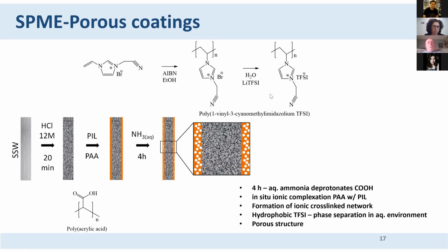So we made, first we etched the wire. We etched the wire, then we dipped it in the solution. So it was a 1-to-1 in weight solution. And then we put this inside of an aqueous solution of ammonia. And what happened was that in situ complexation of the polyacrylic acid occurred since it deprotonates. And so it binds to the PIL and it forms a network. And then we have a phase separation in the aqueous environment since the TFSI is not soluble in water.